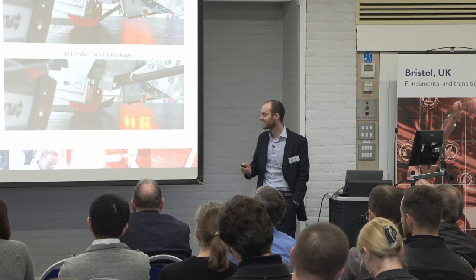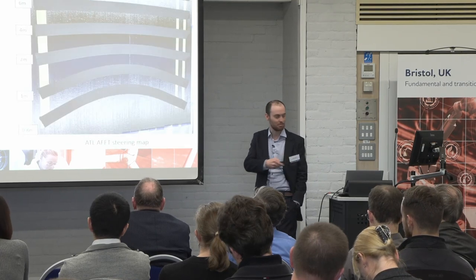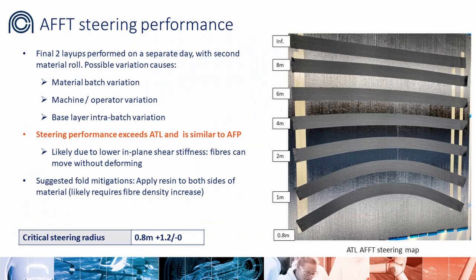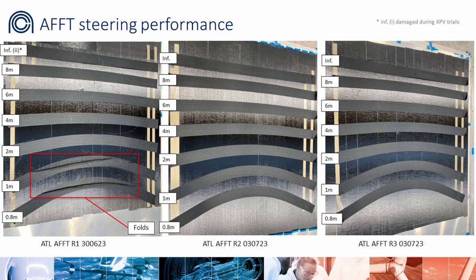But what you want to see here, the important image, is the steering profile. If you have the previous image in your mind, this is a completely different story. I'll show the three trials we did, to be fair about it. Out of the three trials, at 8 meters and 6 meters, the baseline material was what we would describe as unacceptable quality, far too many wrinkles. With the recycled material, the quality is dramatically improved. There's an order of magnitude improvement in quality.